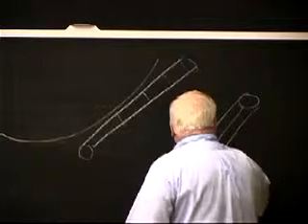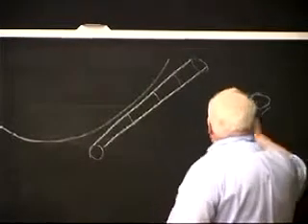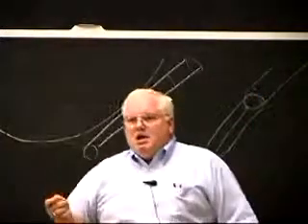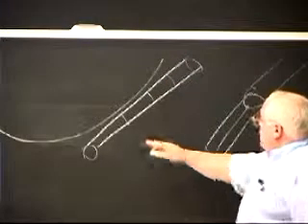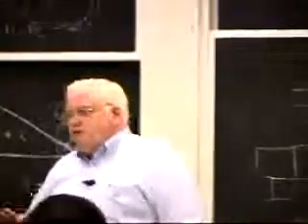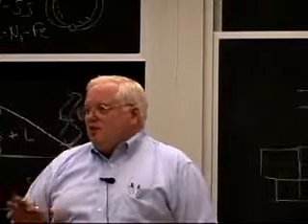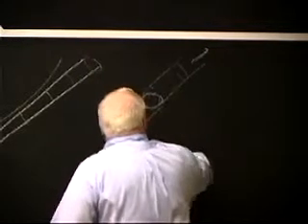and so you have a longitudinal weld, and he had done some special reinforcement at the joints where they had to make their circumferential welds. But the guys using the aluminum plates used the biggest plates they could, and in order to make all these, they put a couple of other welds in between, circumferential welds, that were not in the original design. And so there was no reinforcement on those welds. And this thing had been in service for 20 years without any reinforcement on these aluminum welds that were in the main stress direction, right? Let's stress it this way. The longitudinal welds were not much of a problem.